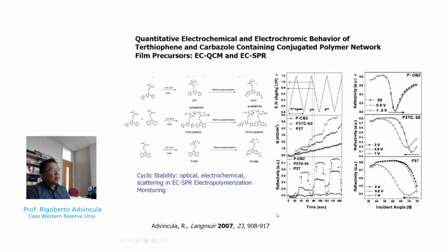with carbazole. But what's interesting is that with reflectivity, we can see the change in the intensity or reflected intensity per cycle. So what you can see here is we go to a phase of oxidation, reduction, oxidation, reduction. In the meantime, as you increase the cycles, you actually increase the reflectivity, which actually when measured under a fixed angle indicates a shift in the Plasmon curve. Now, depending on the voltage, which is a picture of the redox behavior, here are the raw reflectivity curves as a function of incident angle.